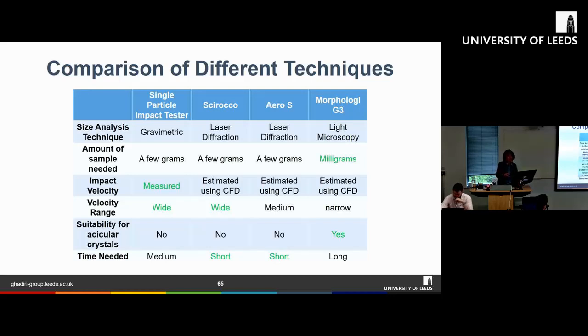And the amount of sample needed for them varies. For the single particle tester, typically we require a few grams of the sample, and the same can be said for Scirocco and Aero S. But for Morphologi G3, we actually need less. We can use milligrams of sample and still perform the breakage analysis of the material.